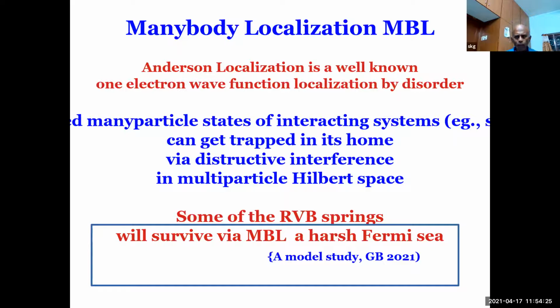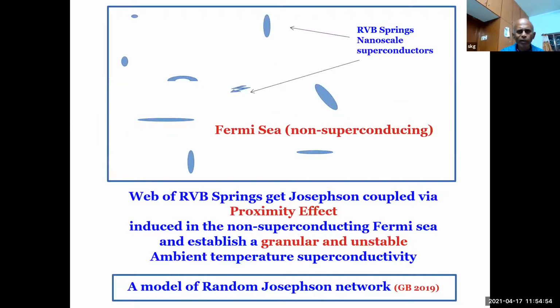So this is what I found is happening here. That's my conjecture. That is, you have gold and you have silver, beautiful Fermi seas. They are very robust. There is no possibility of instabilities, but there are local structural disorders: 100 atoms, 200 atoms, 10 atoms. They support strong local RVB physics, or springs of RVB, but many of them will disappear. However, in the presence of disorder and some doping, some of them could survive.